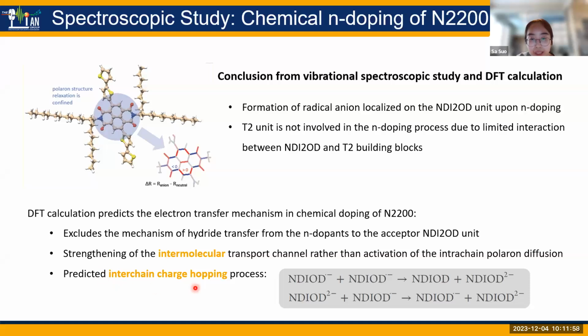And for this mechanism, they believe there could be two possibilities happening. So there could be two interchain radical anions that form one dianion and produce another neutral N2200. Or there could be electron transport between the dianion and a radical anion. So so far, it is the spectroscopic understanding of chemical doping of N2200.